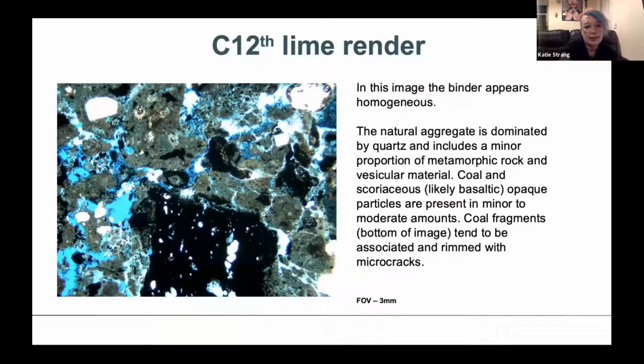And you can see the binder, which is the kind of patchy material here. Now this is quite uniform for a lime mortar of its age. It looks quite similar in density all over. I should point out all the blue spaces are porosity. So with your thin sections, like a rock, you get impregnated under a vacuum with a blue dye, a blue resin, and that just allows you to look at the pore space that's in there.